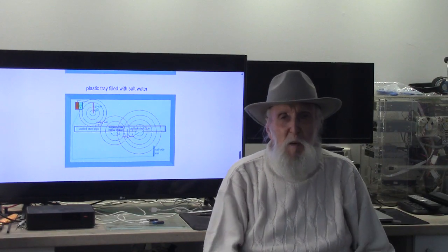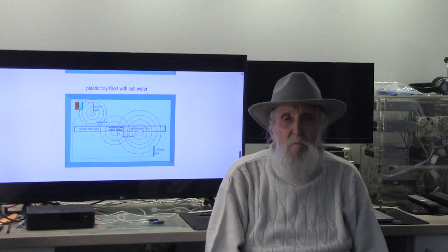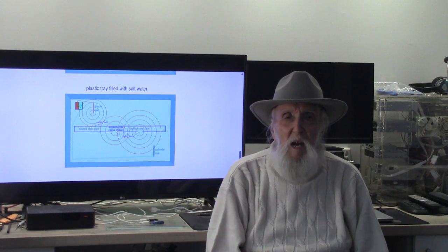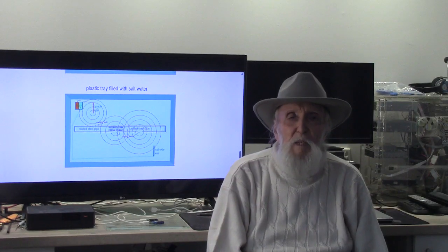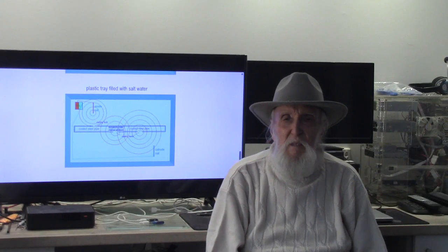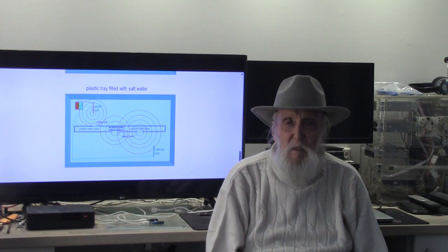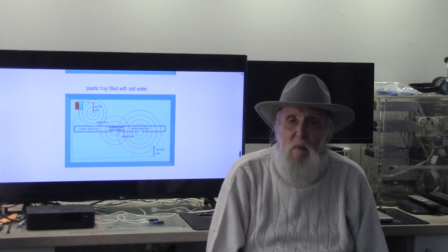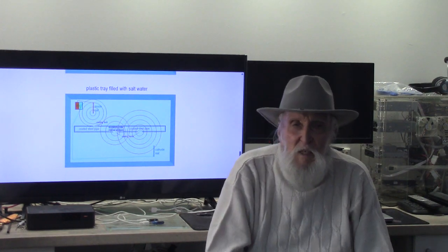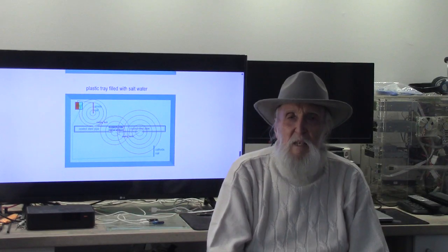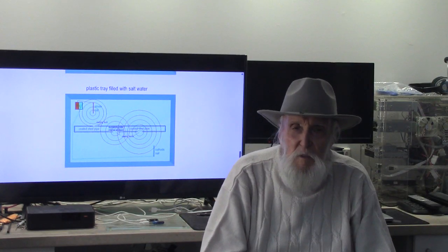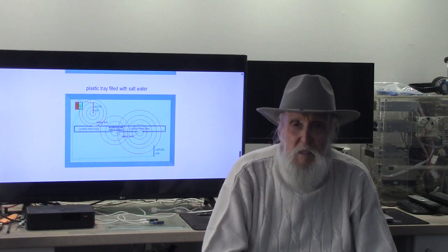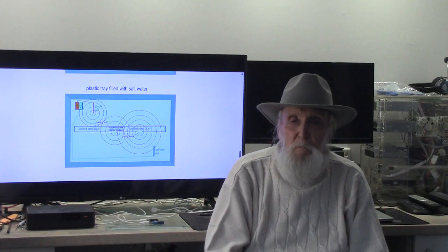Why this matters for pipelines is straightforward. Conventional pipe-to-soil potential readings are a difference between 2 variable points, not an absolute measurement of corrosion current. That floating voltage can be misleading unless you can fix one potential and measure the actual current that is doing the dissolving.